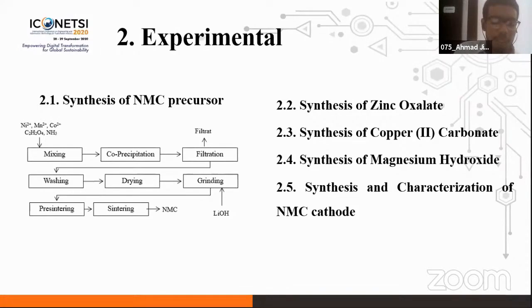Second, synthesis of zinc oxalate. Zinc sulfate solution was mixed with oxalic acid solution, then the solution was aged and filtered. The precipitate is zinc oxalate and ready to use. Third, synthesis of copper(II) carbonate. Copper(II) sulfate solution was mixed with ammonium bicarbonate, then the solution was aged and filtered. The precipitate carbonate was ready to use. Fourth, synthesis of magnesium hydroxide. Magnesium sulfate solution was mixed with sodium hydroxide solution. Then the solution was aged for 24 hours and filtered. The precipitate was dried and magnesium hydroxide was ready to use.